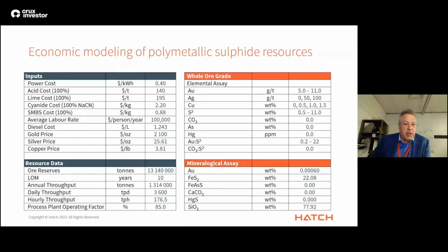However, the model does have the ability to address other mineral types, including arsenopyrite, chalcopyrite, enargite, and pyrrhotite, as well as carbonates. In this model, the silver is recovered through cyanide leaching, followed by carbon absorption, desorption using Zadra stripping, followed by electrowinning and retorting to produce a gold-silver doré. Where copper recovery is desirable, we perform a solid liquid separation after pretreatment, known as countercurrent decantation, and send the copper-rich acidic solution to solvent extraction, followed by electrowinning, while the underflow solids containing the precious metals, gold and silver, are advanced to cyanidation, carbon absorption, desorption, and refining.